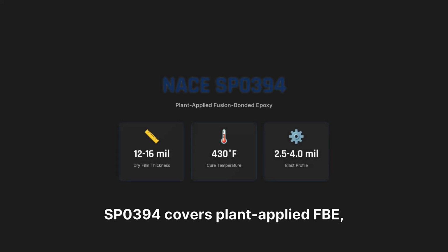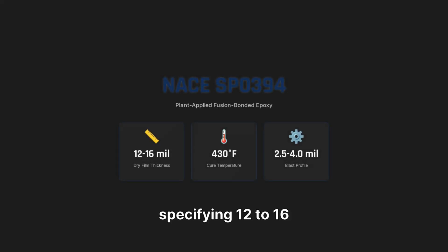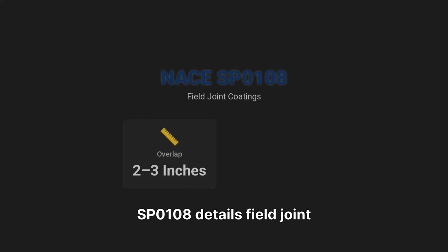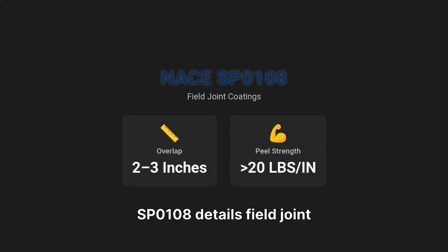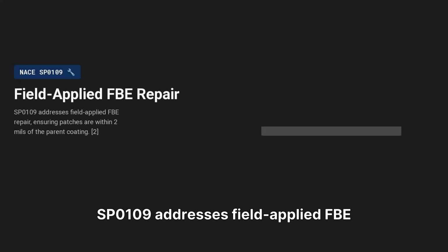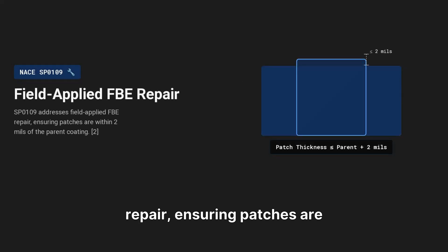SP0394 covers plant-applied FBE, specifying 12 to 16 mil dry film, 430 degrees Fahrenheit cure, and a 2.5 to 4.0 mil blast profile. SP0108 details field joint coatings requiring a 2 to 3 inch overlap and peel strength over 20 pounds per inch. SP0109 addresses field applied FBE repair, ensuring patches are within 2 mils of the parent coating.